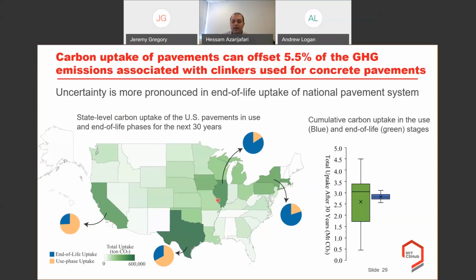While in the state of Illinois or New York, we observed a relatively large carbon uptake, but most of it comes from the end-of-life uptake, the blue part of the pie chart, implying that the composite pavements demolition provides enough demolished concrete at the end of life that will give us the possibility to have an extensive carbon uptake at the end of life.